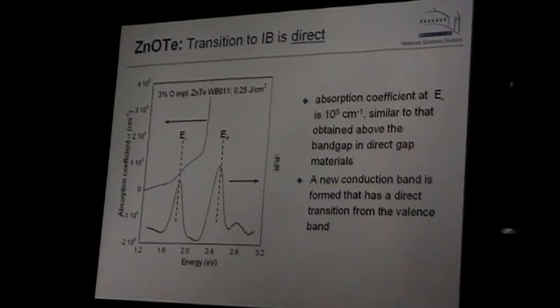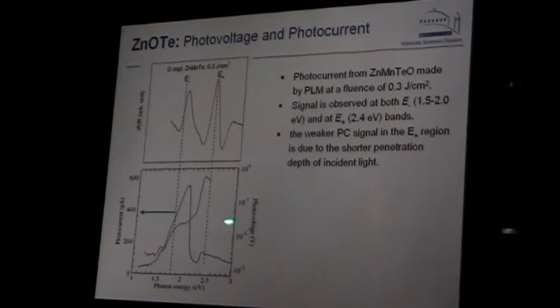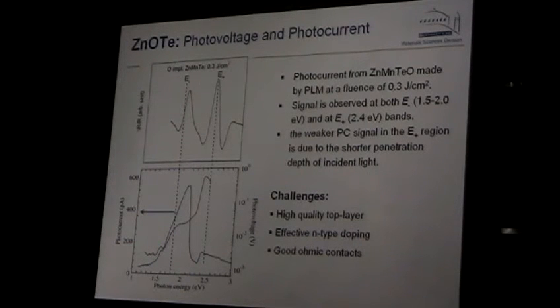So we have basically those two transitions quite well resolved. And that was encouraging. However, we also wanted to check if we can produce any photocurrent in this case. And in fact, we could. This shows the photomodulated reflection, and we see those two transitions as expected. And we see that this is the absorption coefficient, but we see also photocurrent. So there is a photocurrent coming from the transition to the lower energy band, and that was a very good result in a sense. Of course, in this case, we didn't separate yet the intermediate band from the contact. So that was later on.